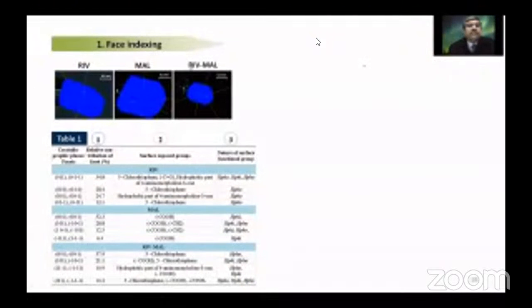The next study was the phase indexation study, which is done using a single crystal XRD machine after generating a single crystal. And this was done for all the three samples: rivaroxaban, pure malonic acid, and their co-crystal. We generated very useful information through this exercise, and we identified the crystallographic planes or the facets in each sample, what was the relative contribution of these facets to the surface groups that were exposed on these facets, and what was the nature of these surface functional groups.